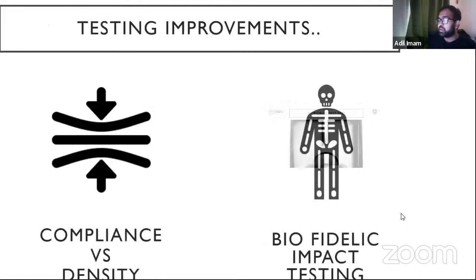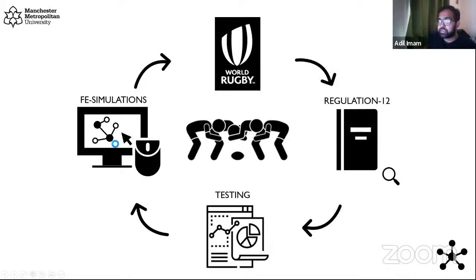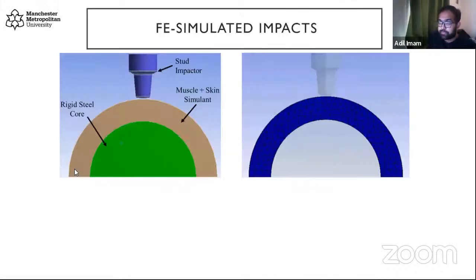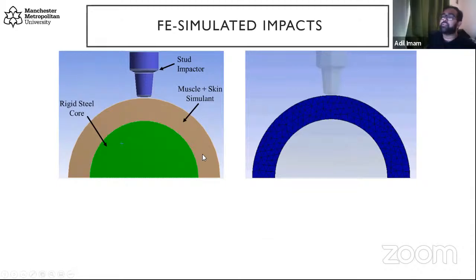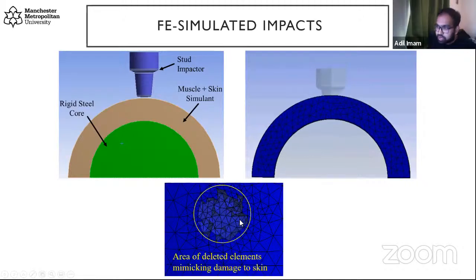Now, using this data, we were able to carry out some FE simulations. So the simulations we did was based on the muscle and skin simulant, which Angus developed. We did some material testing, built our different material model, and then carried out some testing with the stud coming down to see what would happen, and introduced element deletion criteria to mimic the injury that would occur on the human skin tissue. So again, FE simulations are an easier way of simulating such injuries, because we'd never get ethics for testing out on humans and impacting them with stuff to see how their skin reacts. So we've validated this model against our impact testing at different angles, and we've been able to run simulations.